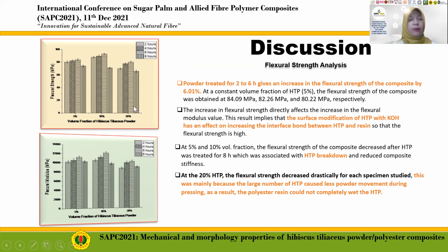At 20% powder, the flexural strength of the composite decreased drastically for each specimen studied. This was mainly because the large amount of powder causes less powder movement during pressing. As a result, the polyester resin could not completely wet the powder.